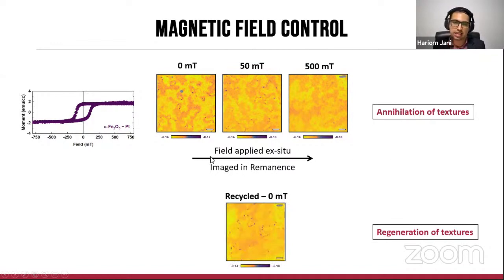And if the system is then taken below the Morin transition and recycled back at room temperature in the absence of any field, we actually recreate the same topological density as compared to what was seen before. This is very important because this shows that this is a reversible process, and this was really important to us because the Morin transition is allowing that accessibility, which unfortunately the Néel transition would not allow, which is placed at much higher temperatures.